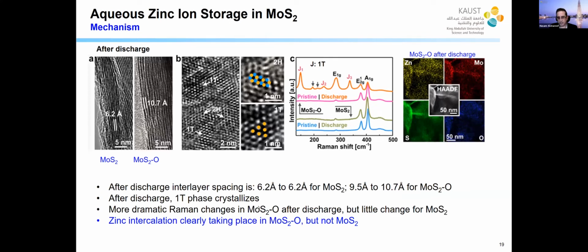So we looked even a little bit more in detail at the mechanism, what happens as the zinc goes in. So this is the molysulfide here after discharge. The word discharge here, for those who are not familiar, means when the zinc goes into the molysulfide. That's called discharge in this arrangement. So in molysulfide, after discharge, the interlayer spacing is not changing. So that means no zinc is going in. But in oxygen substituted molysulfide, after discharge, we have gone from 9.5 to 10.7. This indicates that we have expanded the interlayer spacing because the zinc is going in, it needs space.